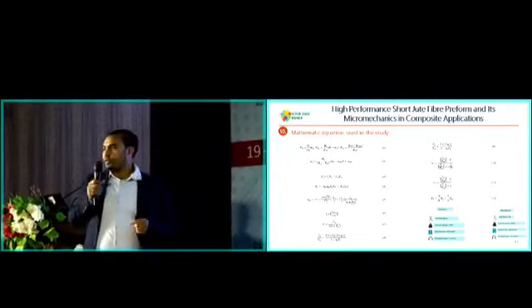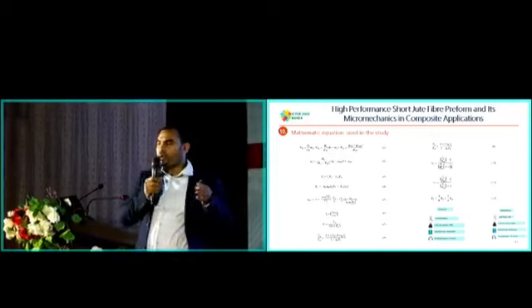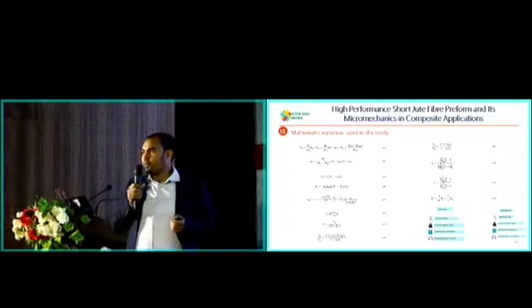And then we also consider the Halpin-Tsai equation, which is used for short fibers and for the transverse direction, to see what is happening with the fiber. By considering the longitudinal and transverse directions, we check whether all the properties are the same or not. So we basically use three mathematical models to fit the experimental data.